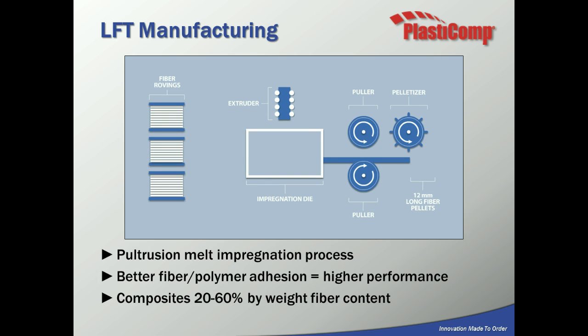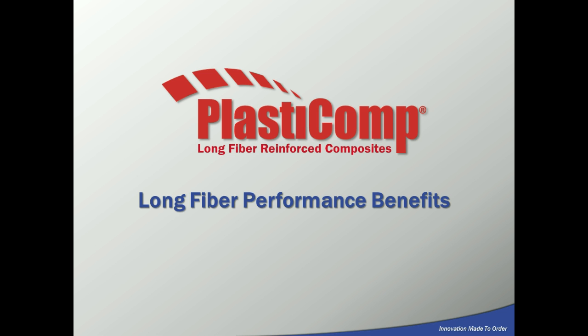So here's a representation of the pultrusion process. If you look over to the left, we start with fiber rovings, and they are pulled through an impregnation die. You can see on the top there's an extruder or melt pump, which is pumping thermoplastic resin in. Again, the goal of this process is to coat the individual fibers, which leads to high mechanical properties and better surface appearance. Those strands are pulled and then brought to a pelletizer, and that pelletizer typically cuts our fibers to about 12 millimeters in length, which is optimal for injection molding processing as well as properties in the final part. Our composites can go anywhere from a 20 to 60% by weight fiber content, depending on the base resin and the fiber type that we're using.